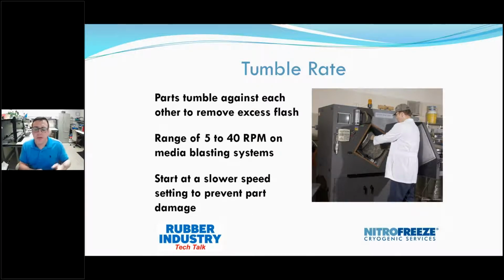What you want to be able to do is remove the flash from the parts via tumbling, but anytime you're using media blasting, you want the media blasting to do the majority of the work. I would say something like three-quarters media blasting, one-quarter tumbling. We find that our best results are at the low side on this one, and that way the media does its job. So we're usually somewhere between 10 and 20 RPM on the tumble rate when we're processing parts.